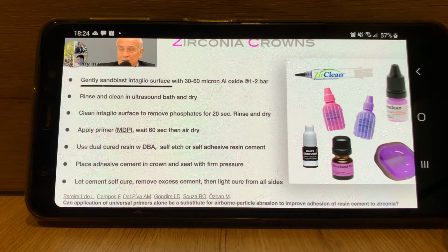There is some controversy among those who do use sandblasting, or I should say air abrasion, a better word for it, as to which material to use; in other words, the size of the aluminum oxide particles, and how much pressure there should be, and at what distance, for how long. I tend to use 50 microns, and the literature mostly seems to concur that it should be somewhere between around 30 and 60 microns, and the pressure about 1 to 2 bars, or certainly not more than 2 bars. You want to do that rather quickly. You don't want to dwell on any one area, and you need about 10 millimeters from the surface. My take on it is, rather than trying to induce any kind of roughness on the zirconia surface, I'm using the sandblasting basically to clean the surface.